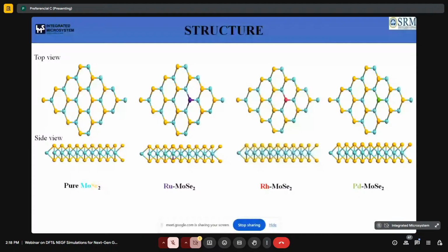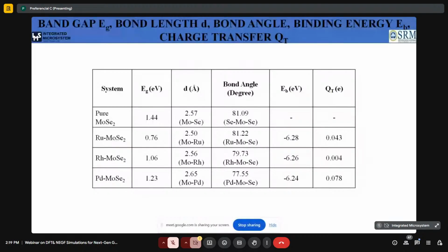After incorporating the dopant into the system, at first we have to confirm whether the structural modification has happened, that is, whether the dopant is properly doped and interacted with the system or not. These are the basic things that have to be analyzed. For that, we have measured the bond length as well as the bond angle. With respect to the pristine MoSe₂ monolayer, the bond length and bond angles show considerable variations.